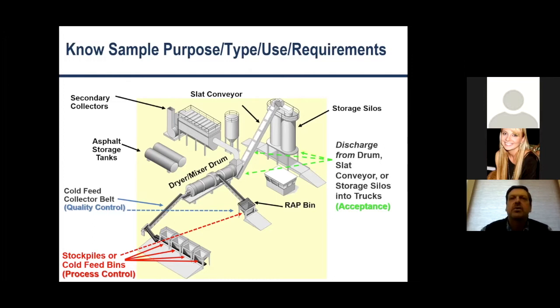And ultimately, though, they're all measurements of gradation, and there may be different methods used. So, like on the mix samples, you've got to run an extraction on it and get the asphalt binder off of it, whether it be with an ignition furnace or with a solvent extraction, so that you can get to the aggregates, where the other two materials, the QC and process control samples, you've got the aggregates directly. So, and you might also, for example, on an acceptance and quality control test, it's really important that you follow all the details of the test methods that are specified, where a producer may, on their stockpile samples, be doing, I don't know, something to accelerate the drying process of the aggregate or something like that, to get quicker answers, especially when you start up at the beginning of the day.